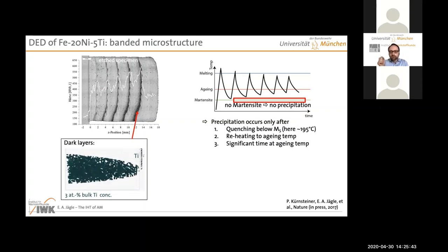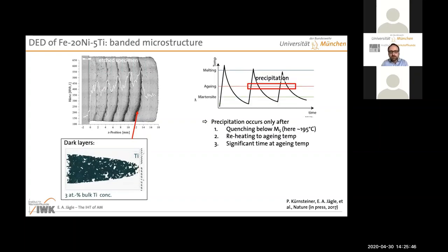And this is precisely where the students got it right with their pause time. If you introduce an artificial pause, you allow cooling down below the MS starting temperature. And then the following reheating peaks are effective. And with this decrease in the hardness, you can see very nicely how the effectiveness of the reheating peaks drops, because this point here where the peak is, that is basically where the pause was. And then all these other layers here are pushing heat down into these layers, which are now martensite after the pause.